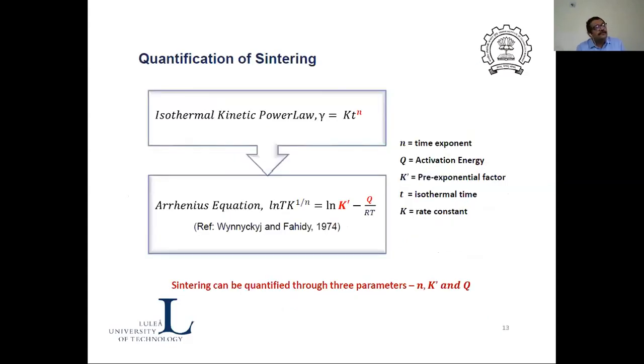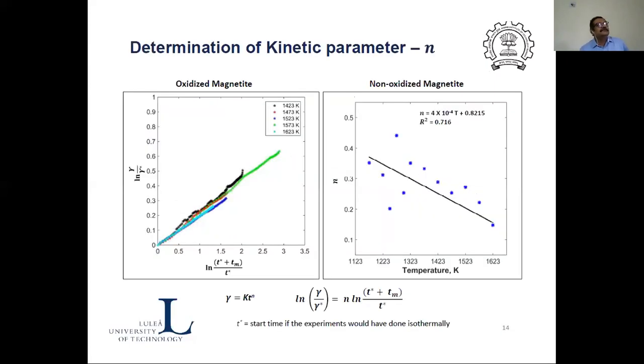And then again, we looked at the powder metallurgy literature. There were actually very nice equations which describe the kinetics of sintering. Of course, those who are metallurgists would have studied, in powder metallurgy, there are different stages of sintering, the different mechanisms and all those things. But as far as iron ore sintering is concerned, we are only at the first stage because we want the pores to be there. So it's basically the first stage of sintering, but in actual powder metallurgy, there are more stages. Okay. So all these equations are already developed. And the most striking thing was when we just put in all those equations, we saw that all those experimental points beautifully, you see how nicely they converged into one line. This was the moment we were so happy. Borrowing from our own friends in powder metallurgy, we could see that actually we can quantify sintering.